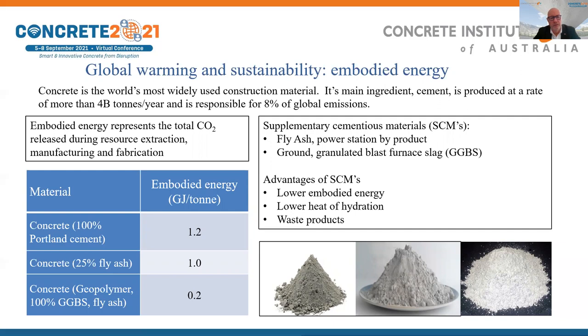And an easy win here is supplementary cementitious materials such as fly ash and blast furnace slag, both byproducts. And you can see with the table there in the bottom left that a simple addition of 25% fly ash, to replace Portland cement reduces the embodied energy by around about 20%. That's got to be worth doing. It not only assists in reducing embodied energy, but allows a lower heat of hydration, so less tendency for early age cracking. And we're also utilizing what's essentially a waste product. So promotion of SCMs, obvious.